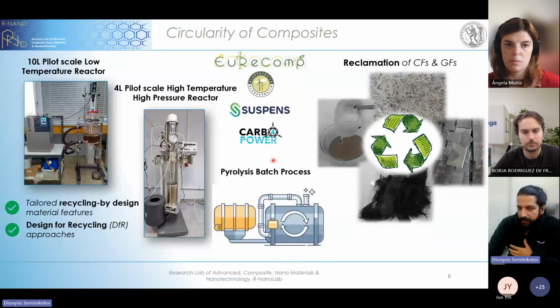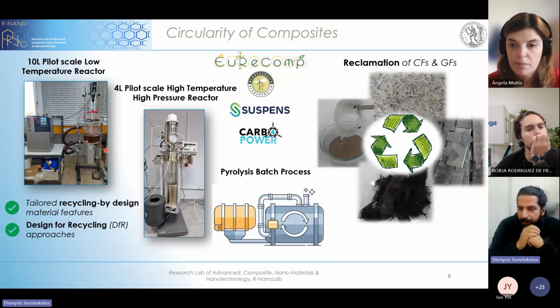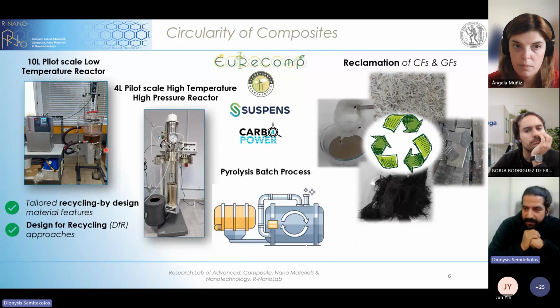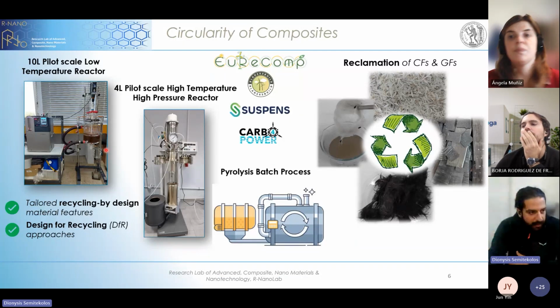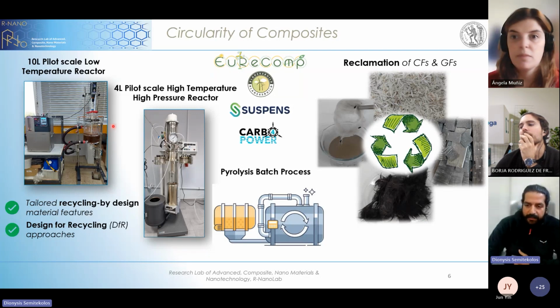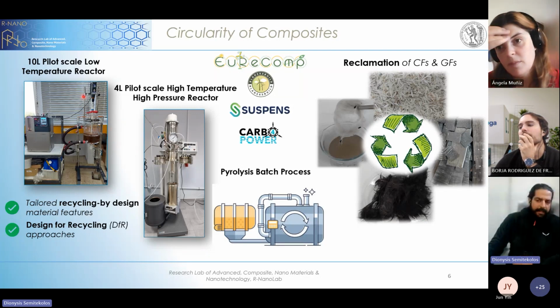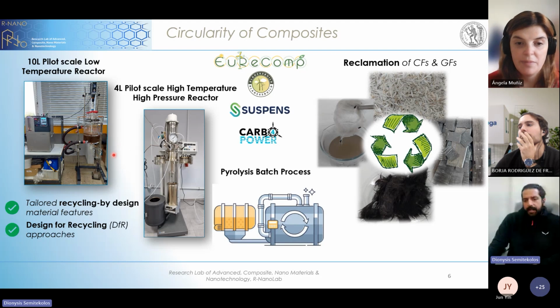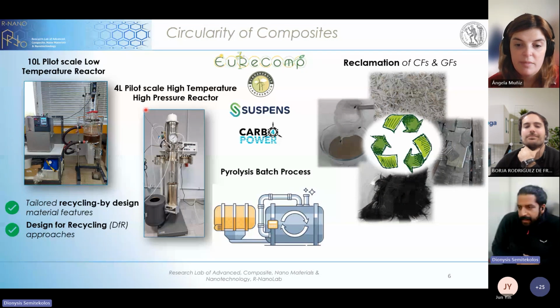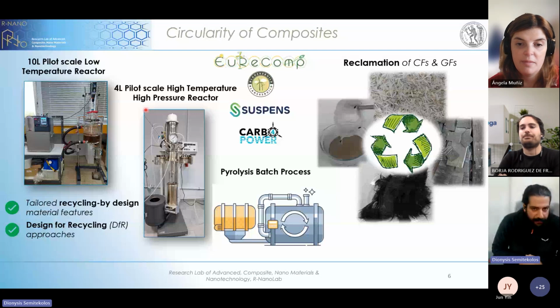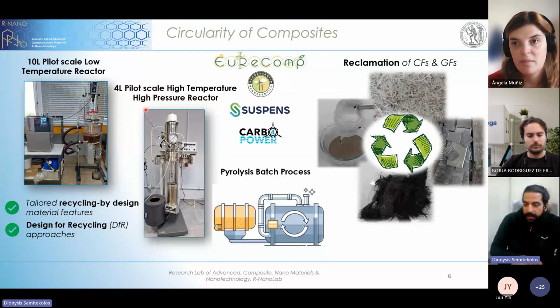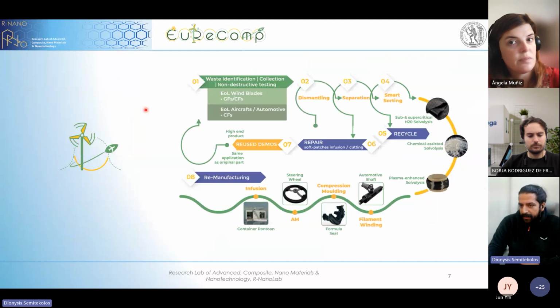In terms of circularity, we have similar processes to what the previous participants have presented, like pyrolytic process or solvolysis. And specifically for solvolysis, we can do either in ambient conditions and also at high pressure, where we can do supercritical solvolysis. All of this, of course, has the meaning to reclaim fibers in their optimal state, and with some modifications, surface treatment and sizing, to improve their mechanical properties.